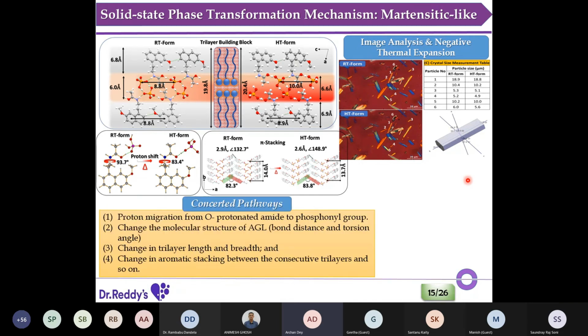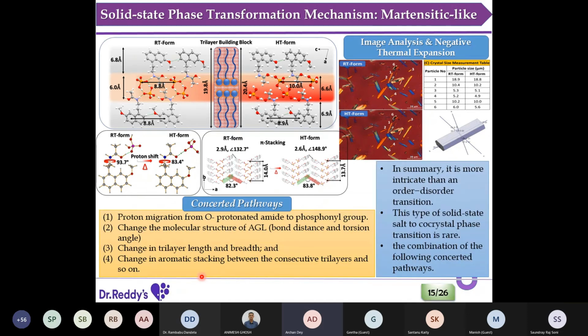Then we thought about the concerted pathway, which could be the following. First, a proton migration from the protonated amide to the phosphoryl group. Then a change of the molecular structure of the AGL, the bond distances and torsion angle. Next, a change in the layer structure, and afterwards a change in the consecutive layers. So practically it's called a layer by layer transformation. In summary, it is more intricate than the order-disorder transition that is generally known for these proton transport materials.